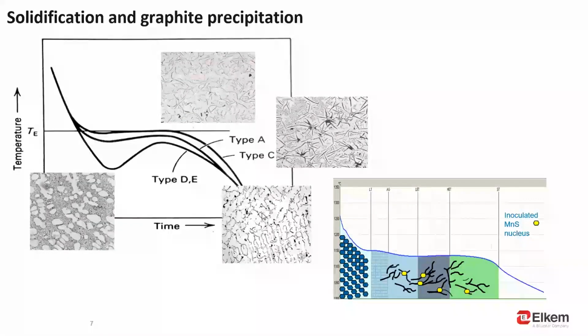As inoculation reduces the dip in temperature, we get better graphite, and the properties start getting much higher. If the cooling is very high, you will get either type D or type E microstructure, or in the worst case, iron carbide. The factor of the right inoculant and the proper size, we have seen in the slide. Consider the section thickness of the casting.